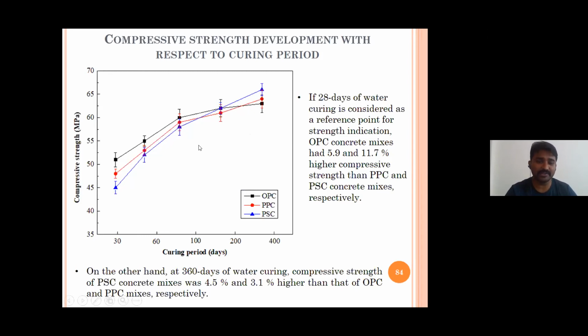And I'm happy to share that the PSC concrete gains strength at a later point of time. If you observe at 1 year, the strength of OPC concrete is also increasing, but there is significant improvement in the PPC and PSC concrete at the age of 1 year. From this, we can say that the PPC and PSC concrete is slow in gaining the initial strength, but at a later stage it beats the OPC. The major reason for this sudden increase in compressive strength is pozzolanic reactions.